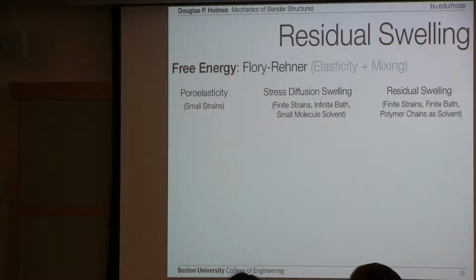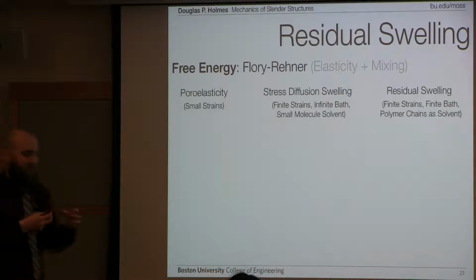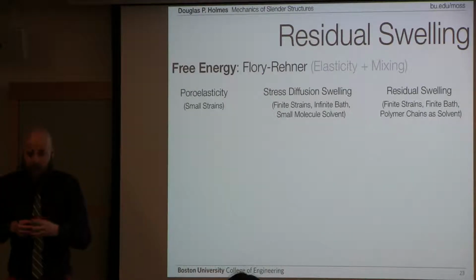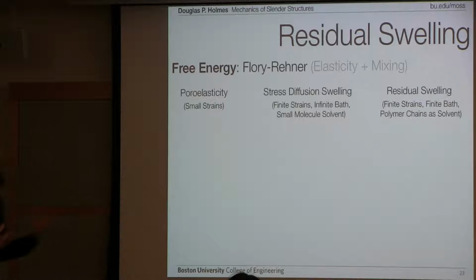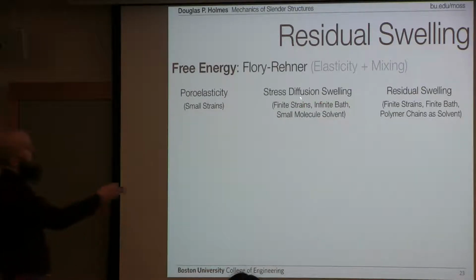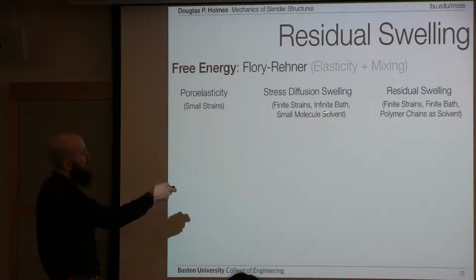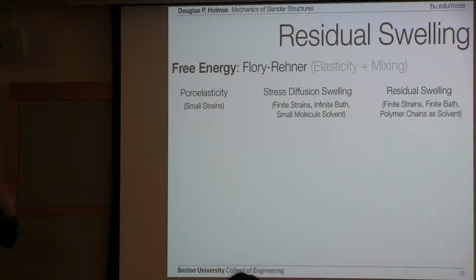This was developed by Maurice Biot in the 1940s to understand soil mechanics, in which you treat the soil as an elastic structure and the fluid as your swelling solvent, and you can study things like how soil will consolidate. For larger strains, like for instance taking a hydrogel, which can change volume by hundreds of percent, you have to do a little more work. You have to consider finite strains, you have to consider that there's an infinite bath of fluid, and you have to think about the solvent as a small, maybe water molecule. This gives rise to a theory known as stress diffusion swelling.